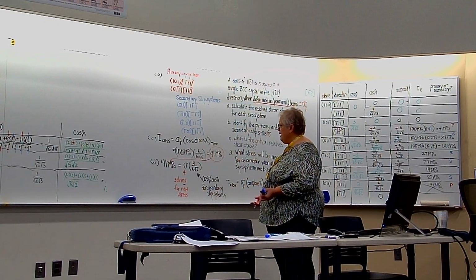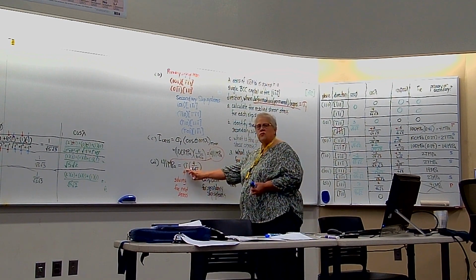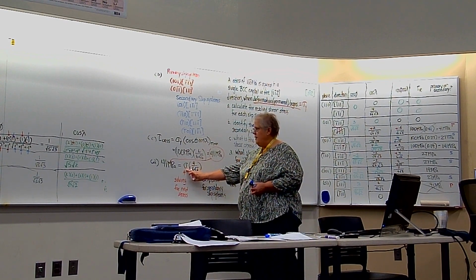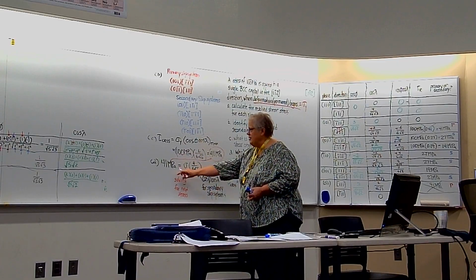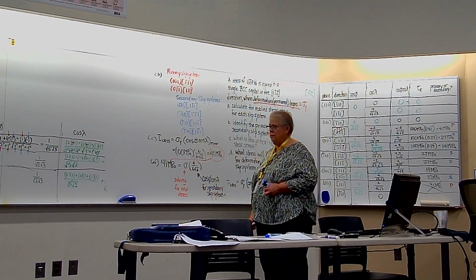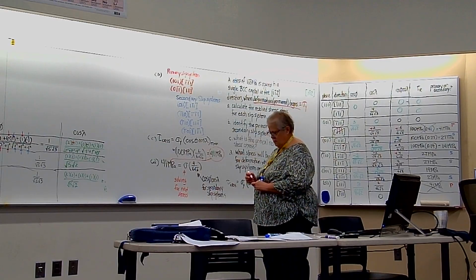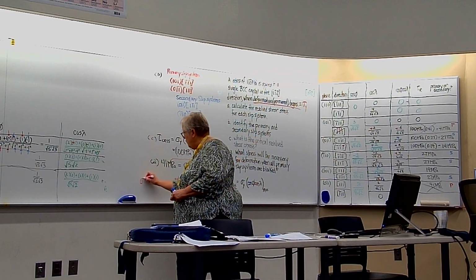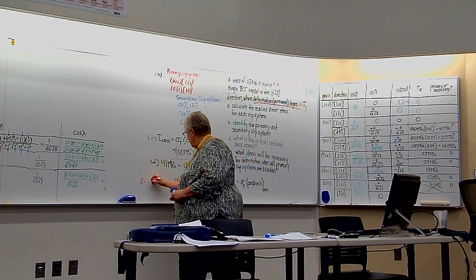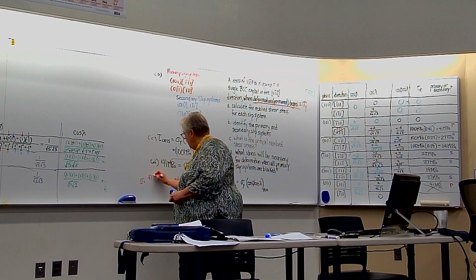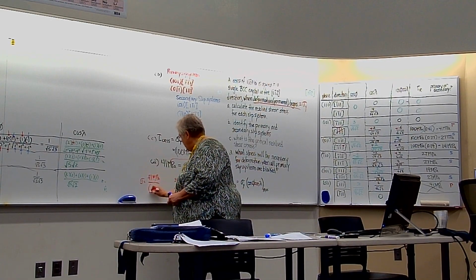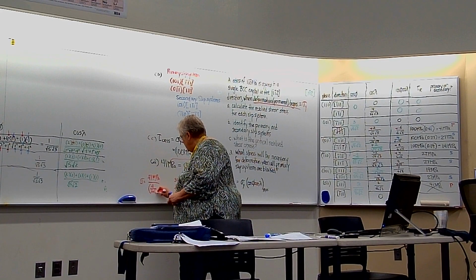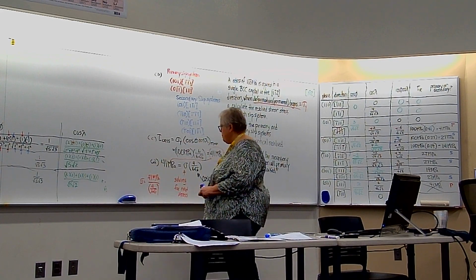So now we need to find out how big the applied stress has to be in order for this product to equal the critical value. So that new stress has to equal 41 megapascals divided by 4 over 6 root 6.